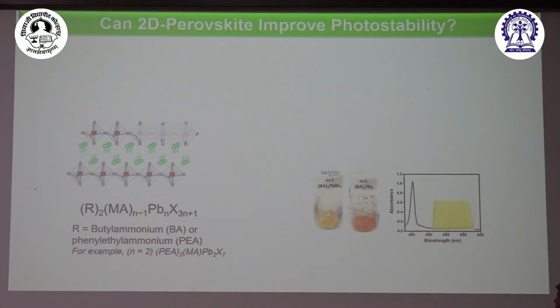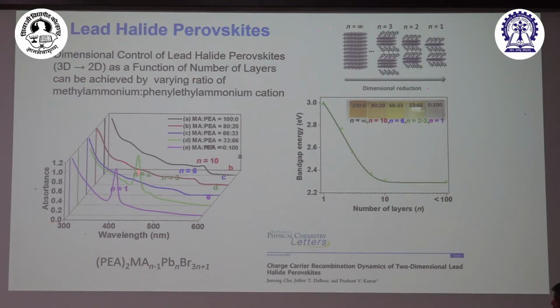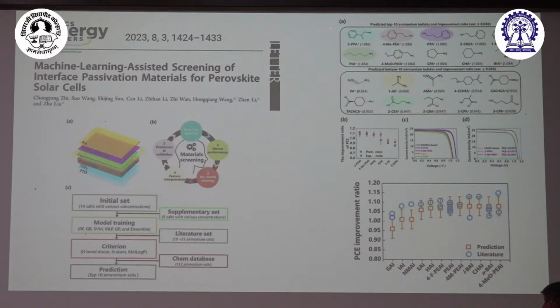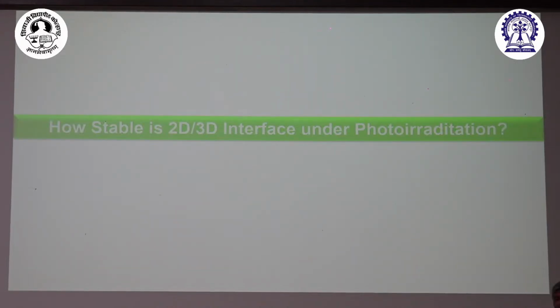And so this is the 2D perovskite I talked about yesterday. This absorption spectrum, you can change the layer numbers. So notice that when you change the layer numbers, the absorption shifts to the visible, okay? They have characteristic fingerprints for this. Again, there are various sets of studies done, and these guys have even calculated the PCE improvement ratio. They say that if you have this, these ones are better, whereas these ones at less than 1 are not better. So again, they have done a machine learning analysis of the data. Okay, so again, as I said earlier, if everybody is going in one direction, sometimes somebody has to look in the other direction, right?